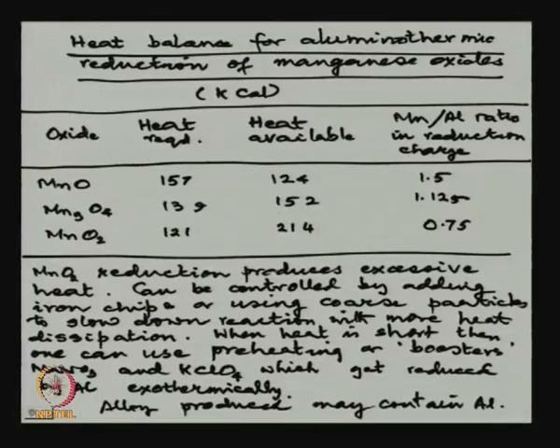It can be absorbed by adding iron if you do not mind producing a ferromanganese, or else if you do not want ferromanganese, you want manganese, then you add some manganese you already had, cold manganese, which will absorb heat and mix with the manganese that you are producing. So, it is a diluent. On the other hand, if you find the heat available is less than the heat you require, then you have to put in booster reactions, add chemicals like sodium nitrate or potassium chlorate, which will get reduced by aluminum exothermically.